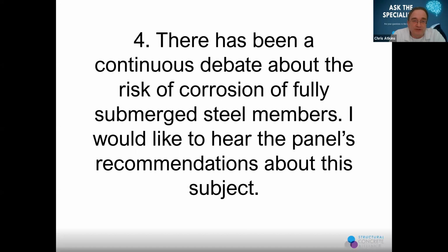And for permanently submerged, just conventional steelwork, the corrosion rate will certainly decrease typically when it's submerged. But there are examples where you'll get a more accelerated corrosion because the environment changes, because there is a lack of oxygen, you then get a proliferation of microbes. Anybody got anything else to chip in?